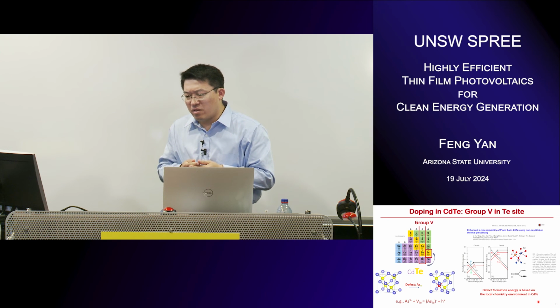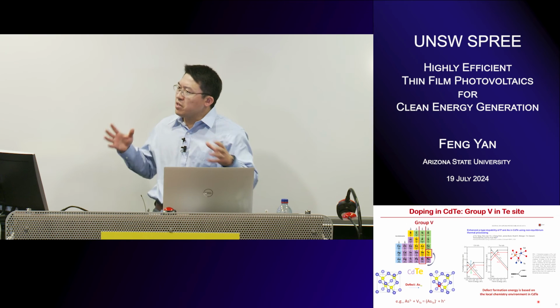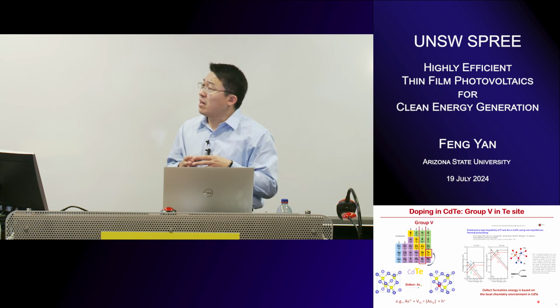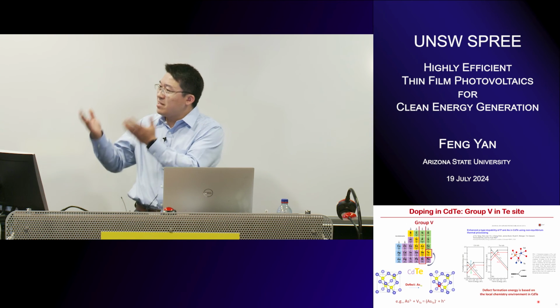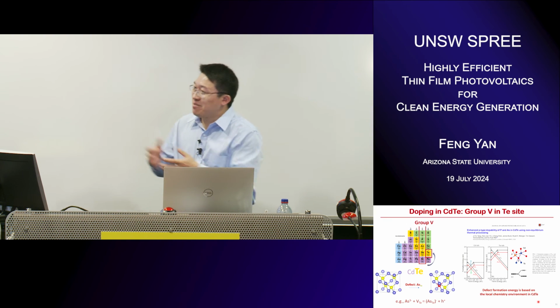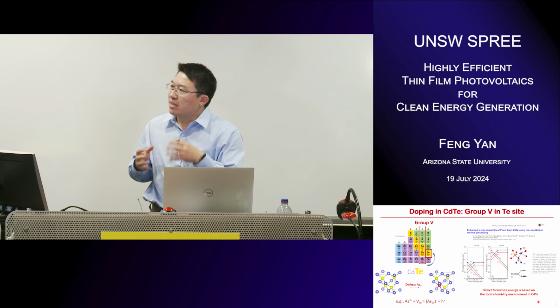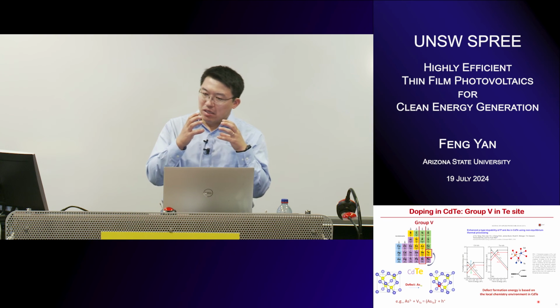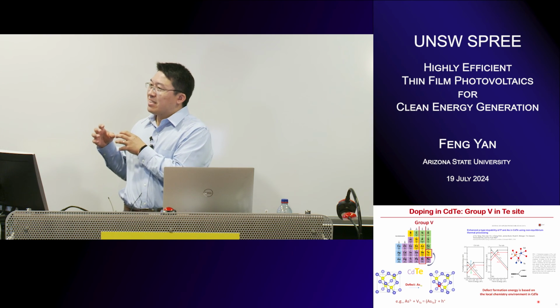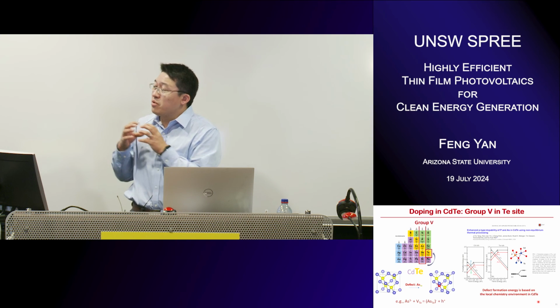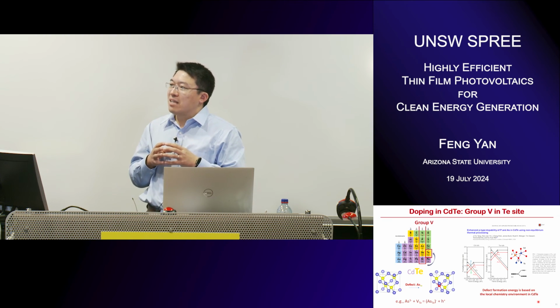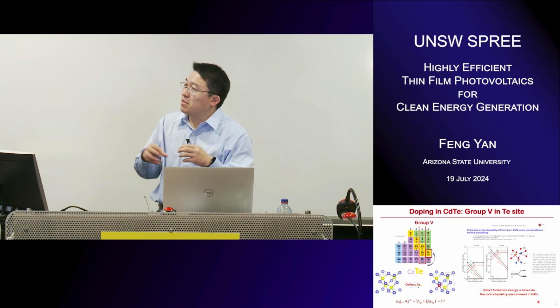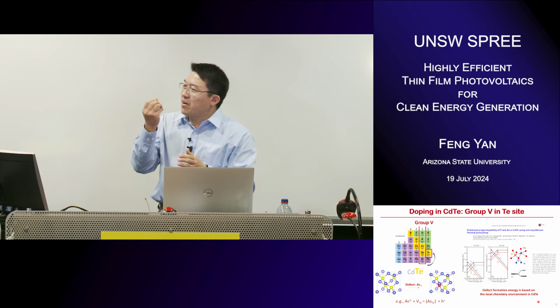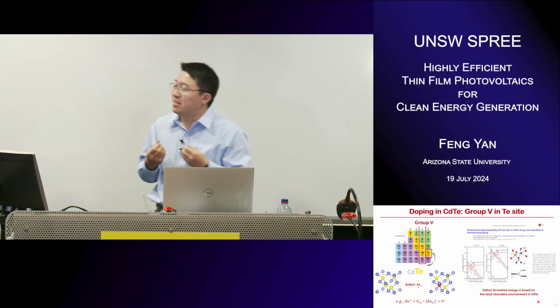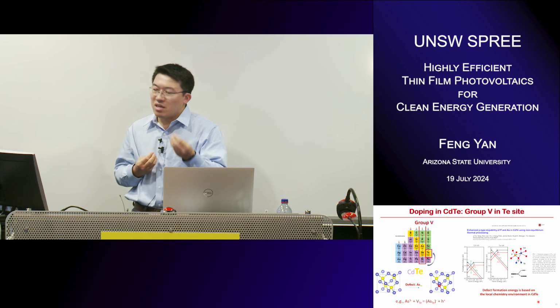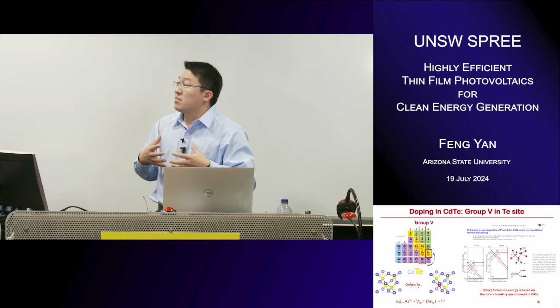So overall, it's not a single role, as we mentioned. It may not be limited to cadmium telluride. For perovskite, probably methylammonium chloride, right? For CIGS, probably some potassium element. So I think each individual absorber should have a corresponding chemical, known or unknown, to realize this role. That's a pretty unified concept. Some groups call it a flux that melts during the chlorine treatment, and then grain growth, passivation, and doping are realized together.